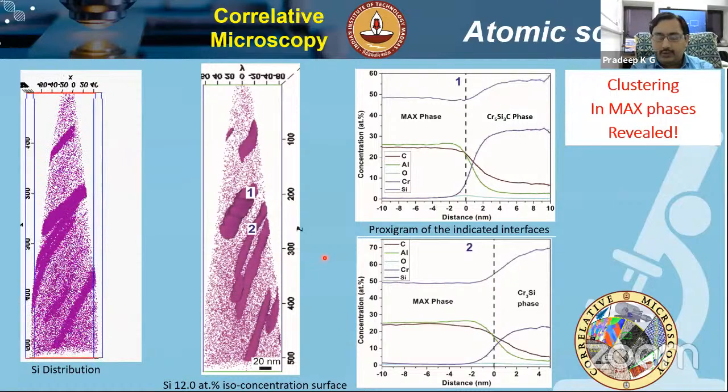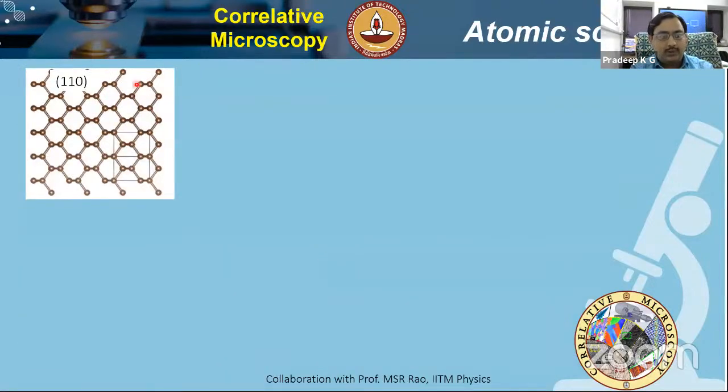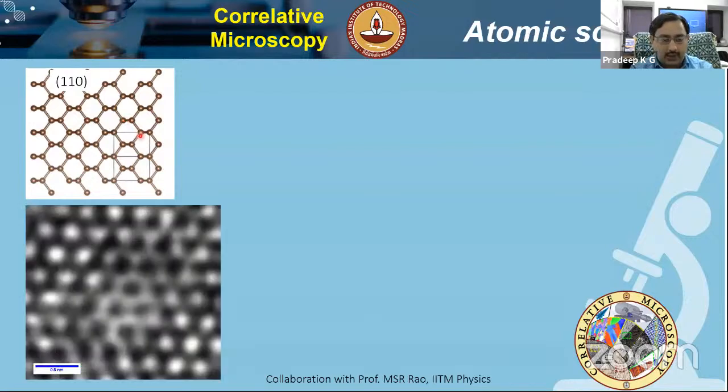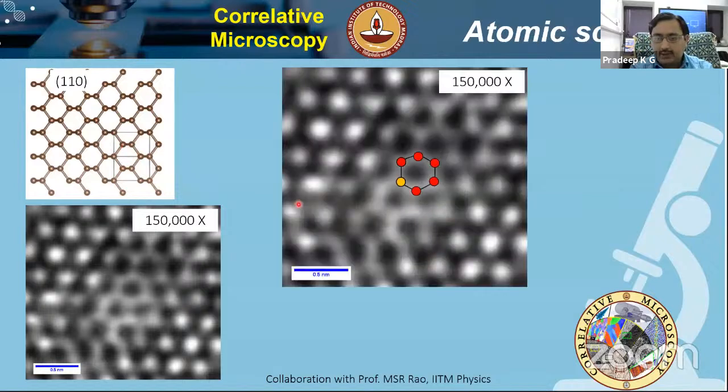So this enables us to discern, even at the nanometer scale, variations among different local structures. If we now continue with the atomic scale, this is an arrangement of one of those diamond structures in one specific orientation. If we now really want to see the atomic positioning, then we can go into high resolution microscopy and look at the same type of atomic arrangement at very high resolutions. And you can see this hexagon is nicely visualized. And there are locations where this atomic arrangement has a missing atom. That means an open bond here.